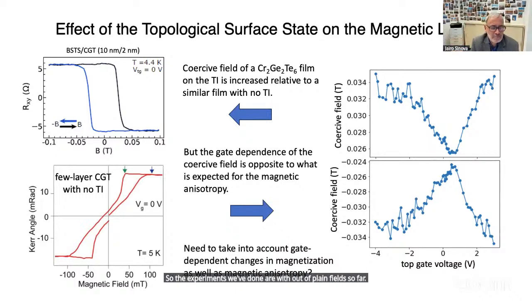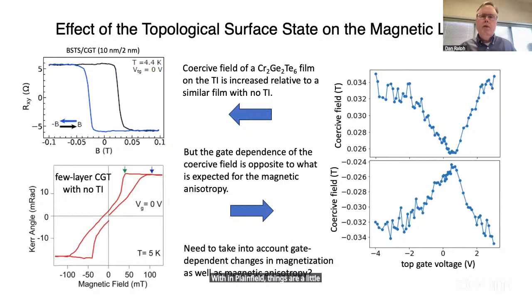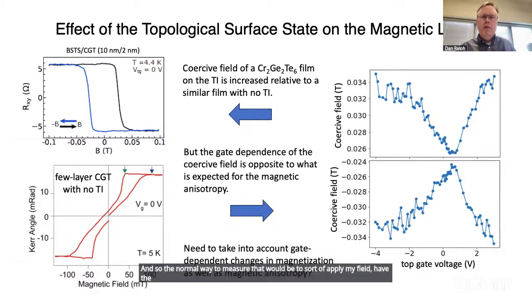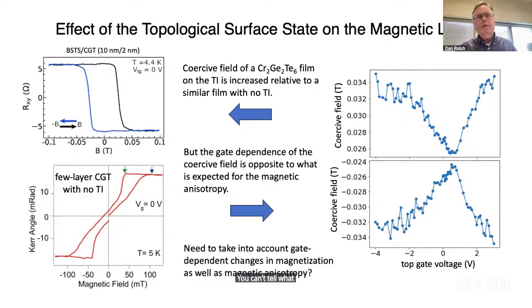With in-plane field, things are a little bit trickier trying to measure anisotropies that way, just because you're close to a quantized value of the Hall resistance. And so the normal way to measure that would be to apply magnetic field, have the magnetization tilt, and measure the tilt from the change in the Hall resistance. But if the Hall resistance isn't changing as a function of tilt, you can't tell what the anisotropy is that way. Very good. That's an interesting result.